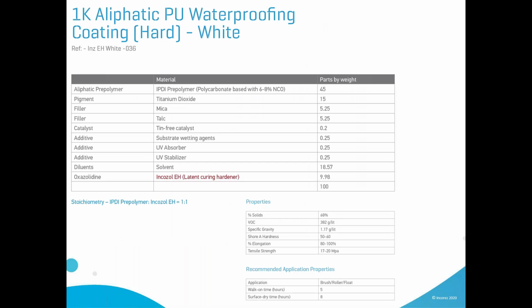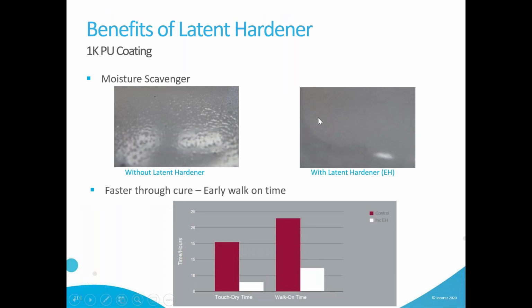This is a typical PU1K formulation you can achieve with IPDI and Incozol EH for flooring, balcony, and roofing. And on top of the defect-free appearance you get from the moisture scavenger effect, you also have a faster through cure. As I explained, the Incozol 4 and EH work as latent hardeners and cross-link your system, so the overall film will dry faster thanks to that. You can see here that thanks to Incozol EH, your walk-on time will be basically half. So instead of having a 1-day curing time, you have 12 hours. Another way to see it is that you will be able to have a decent drying time, even at lower temperature.